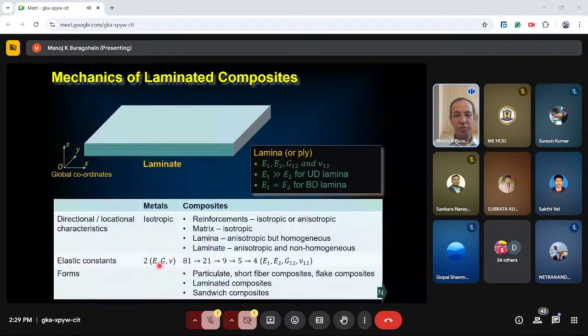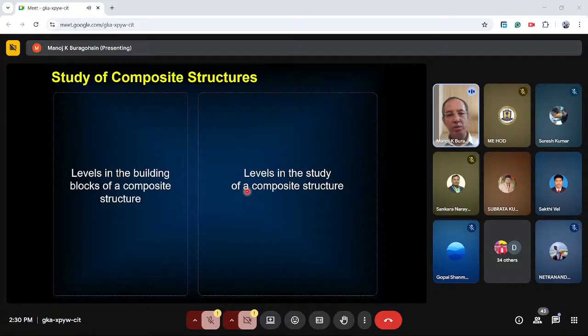For example, we would know that for an isotropic material, we have two independent elastic constants: E, G, and nu, out of these three, any two are independent. Whereas in the case of composites, this number can actually be 81, but under a number of assumptions or simplifying criteria, this number can progressively be reduced to 36, then 21, then 9, then 5, and finally 4 for plane stress conditions, where we have E1, E2, G12, and nu12. And these four elastic constants would actually define a lamina or a single ply in our laminated composites mechanics.